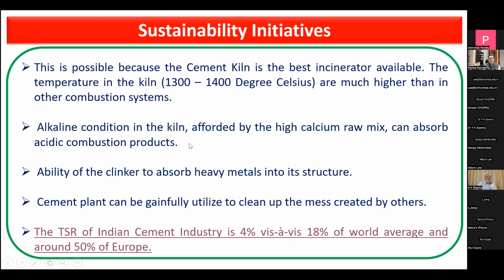The reason we are able to do this is because the cement kiln is the best incinerator available. The temperature inside the kiln is 1300 to 1400 degrees, which is much higher than any other combustion system. Alkaline conditions in the kiln, afforded by the high calcium raw mix, can absorb acidic combustion products. And there is the ability of clinker to absorb heavy metals into its structure. With all these things, we are able to burn hazardous waste with the least environmental impact, and we are able to dispose of everything in our kilns.